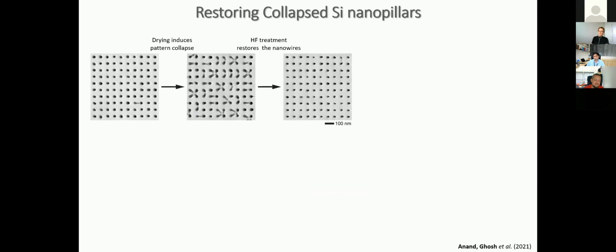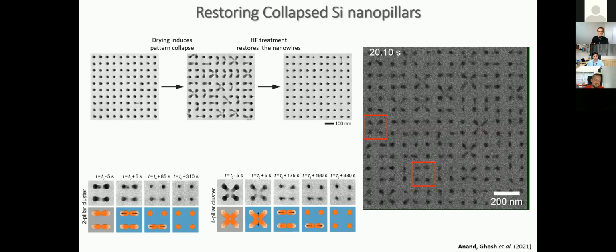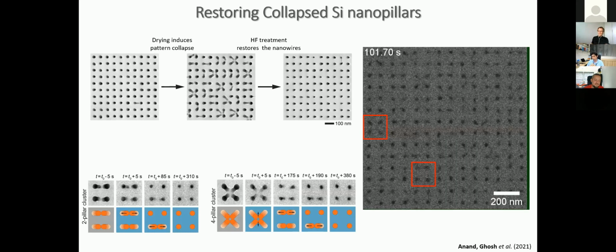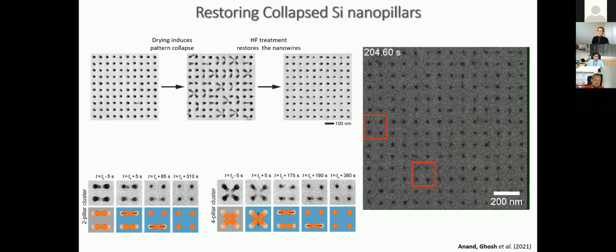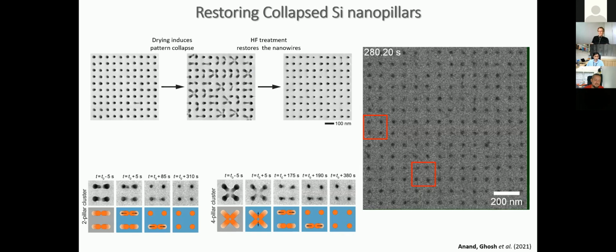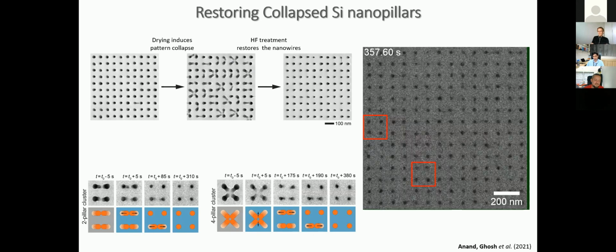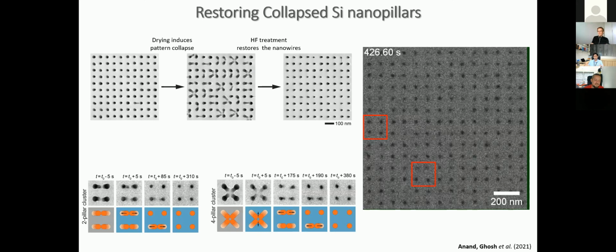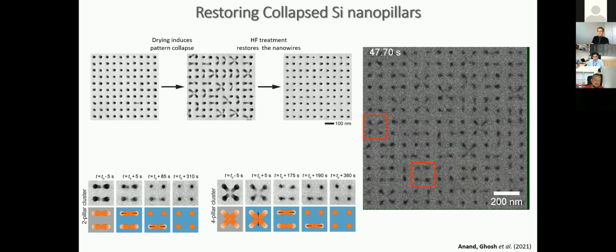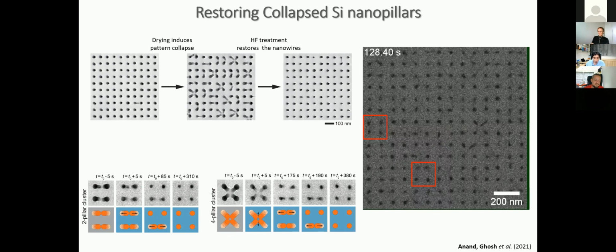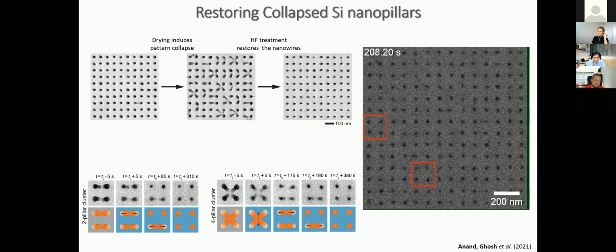Okay, can we visualize? Well, keep in mind, HF is not a friendly acid. If you spill it on yourself, you're not going to feel it until your bones start melting away, right? So you have to be very careful, and especially doing this inside an electron microscope, because you don't want to contaminate your lenses, because at some point engineers will have to take it. So you have to really let them know what kind of experiments you do. And here what you have is actually the nanopillars in the presence of the HF inside the microscope. That's why I'm telling you, we have to design the holders ourselves. We always work with this unfriendly chemical. And what you see here is nanopillars that are stuck originally when you introduce the HF.